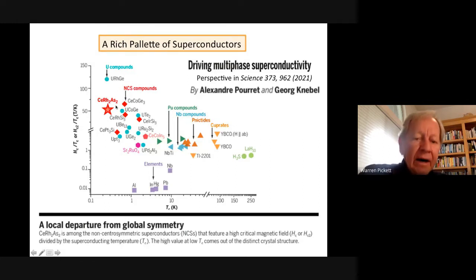It would just be a straight line across here. But you see that although a lot of the materials occur right in here, the elements are down here, a completely different value. Again, a log plot of this quantity. The heavy fermion compounds, cerium-based and uranium-based, are over here in the green and the red. The iron-based materials, I think, are shown here. There are three plutonium compounds here, which are actually heavy fermion materials also. And here, the iron-based materials, called pnictides, and the cuprates, and then the hydrogen-based materials.